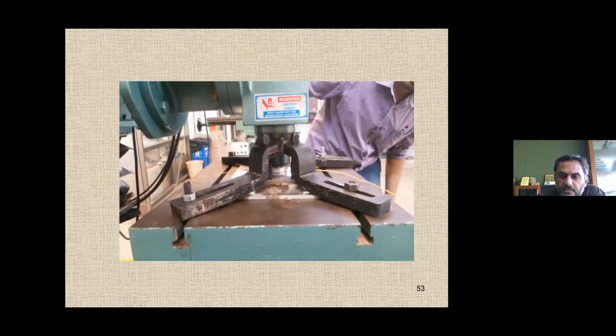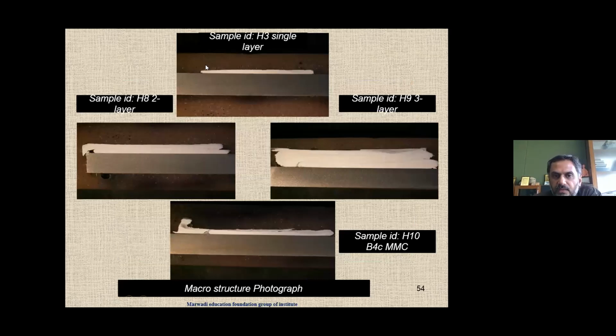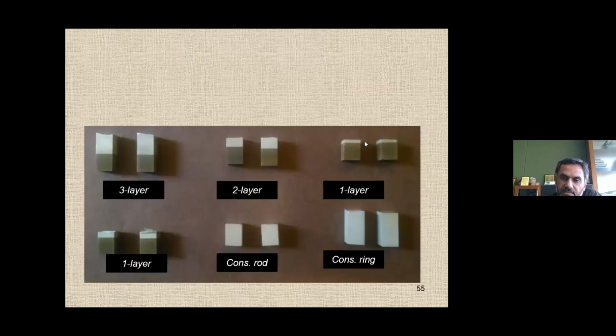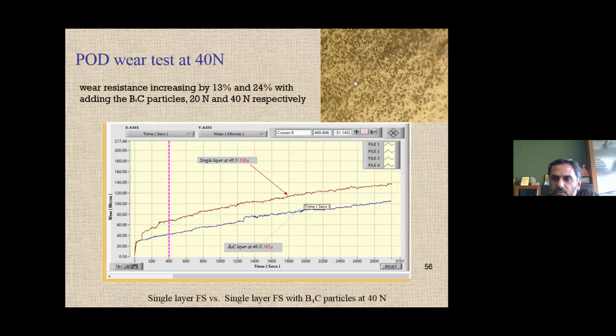So this is called friction surfacing. What we have done in our lab, we deposited 1 layer of aluminum, 2 layers of aluminum, 3 layers of aluminum. But in this single layer, we have introduced the boron carbide particles through the aluminum rod. You saw there was a video. So at the center, we created a drill, a blind hole, and then we filled that cavity with the boron carbide slurry. And then we started the friction surfacing, and those boron carbides become part of the layer. And then we did the wear testing also with the single layer, double layer, and the boron carbide layer also. And we found those boron carbide particles in the aluminum layer which has been deposited.